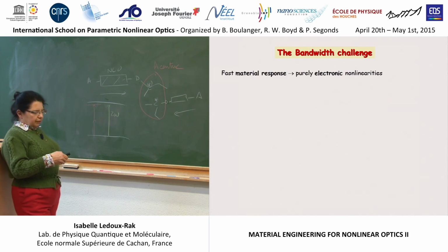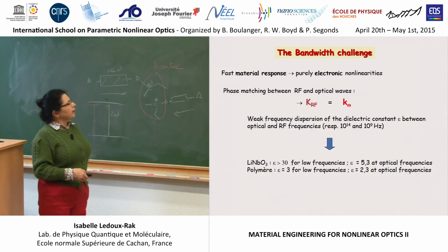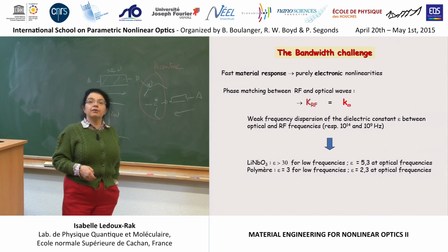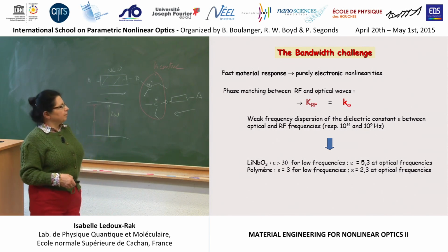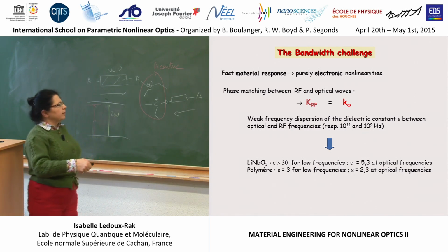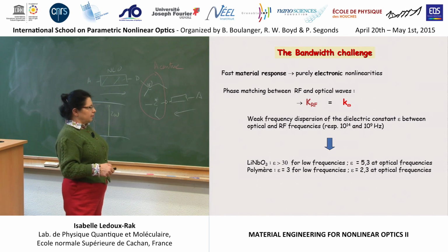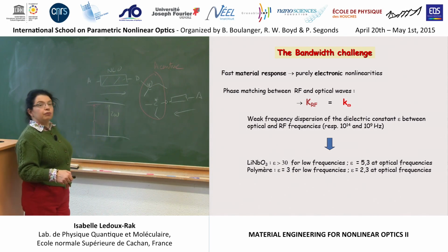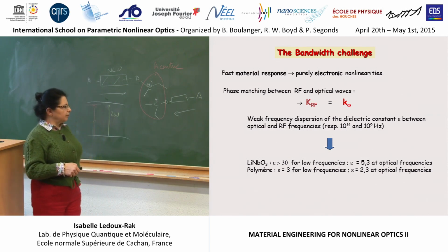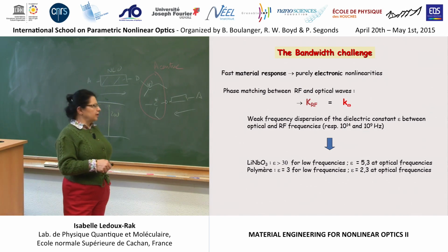For material response, to have a wide bandwidth, we must have purely electronic nonlinearities, and we must have phase matching between radio frequency waves, which are sent onto the device, and optical waves. And this is found when there is a weak frequency dispersion of the dielectric constant between the optical and radio frequencies. And this is not the case for lithium niobate, because epsilon is large for low frequency and small for optical ones. In the polymer, these epsilon values are almost the same, because in lithium niobate you have some other contribution, non-electronic contribution to the nonlinear response.